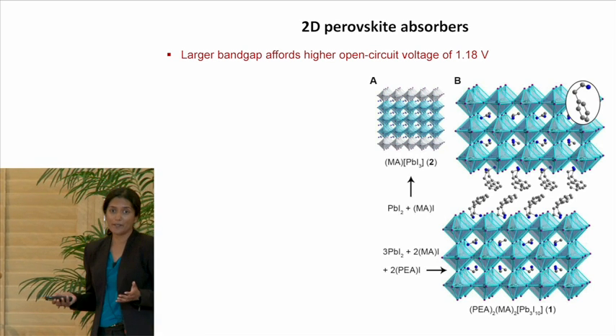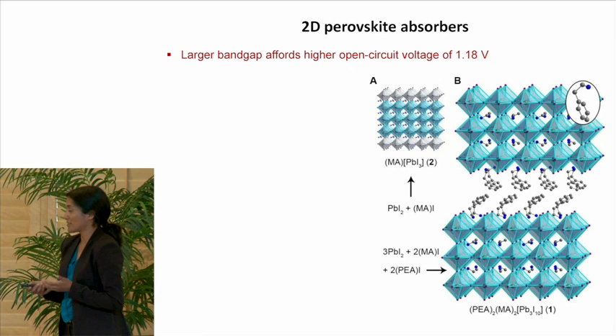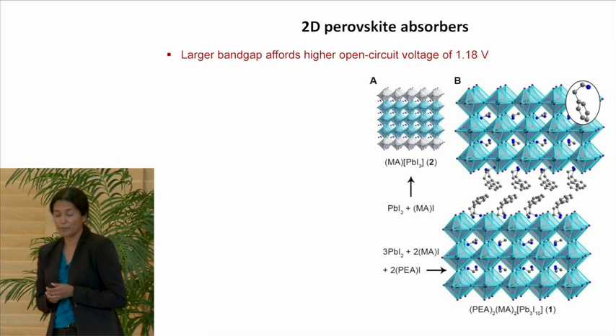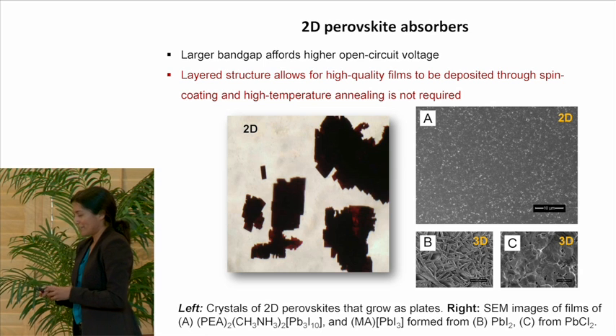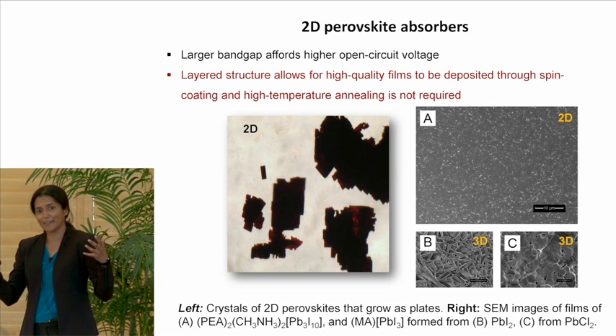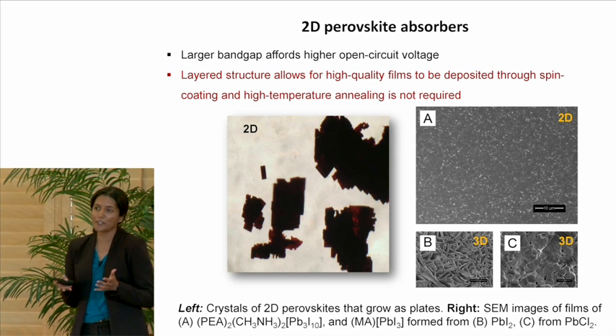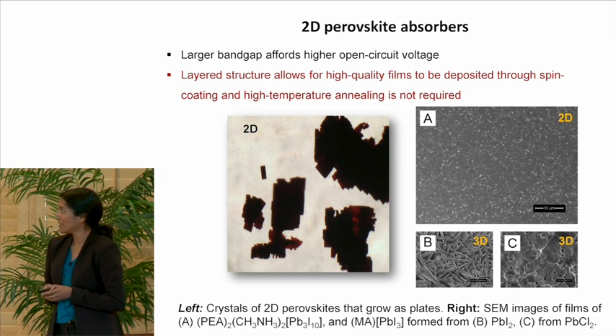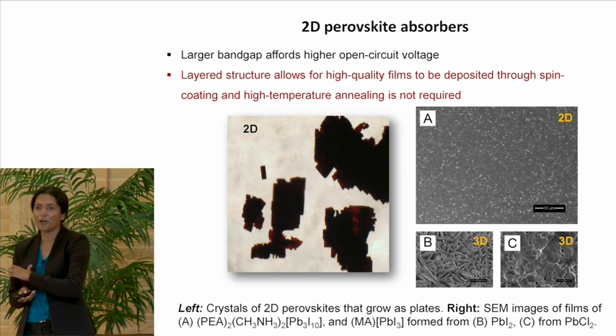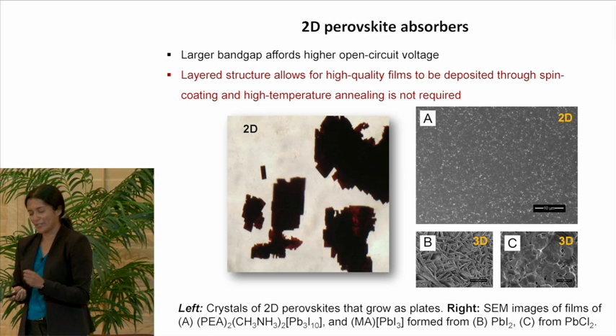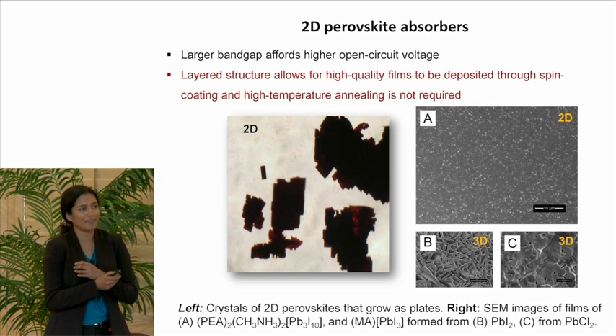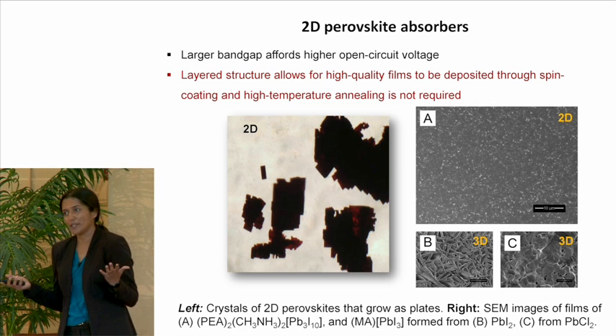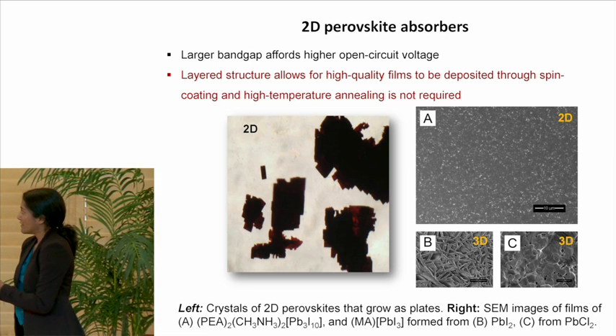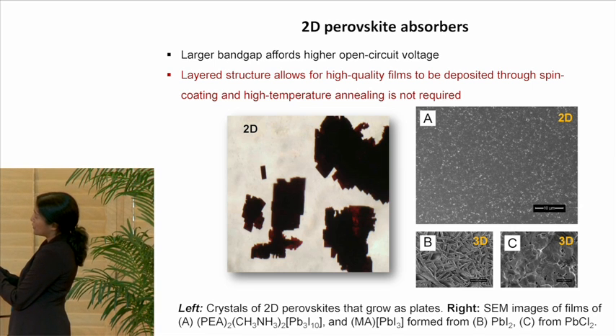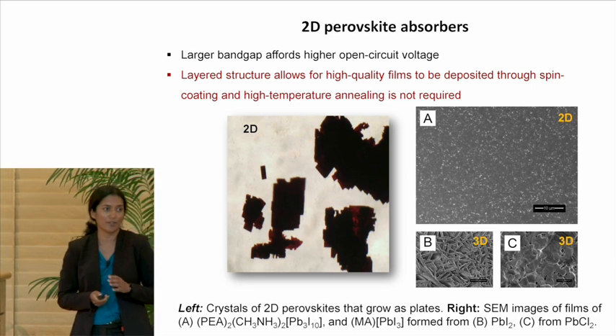So for one, this has a larger band gap, so we can access higher voltages. These voltages are higher than any voltages that have been achieved with the 3D perovskite solar cell. The structure is layered, and therefore these materials grow as plates. This is in contrast to 3D perovskites, which grow as cubes or blocks. And because of this layered structure, these materials love to form beautiful uniform films. So we can simply drop cast this material on a slide and this doesn't require any kind of high temperature annealing. We can form nice continuous films. And here I show you a film of the 2D perovskite, and in contrast, similar deposition techniques for the 3D material don't give the same nice surface coverage.